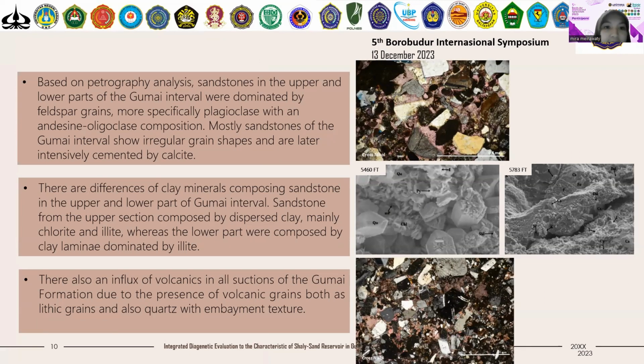Based on petrography analysis, sandstone in the upper and lower parts of the Gumai interval were dominated by feldspar grains, more specifically plagioclase, with an andesine-oligoclase composition, as we can see by here. Mostly sandstone of the Gumai interval show irregular grain shapes, and they were later intensively cemented by pink color calcite. There are differences of clay minerals composing sandstone in the upper and lower part of the Gumai interval.